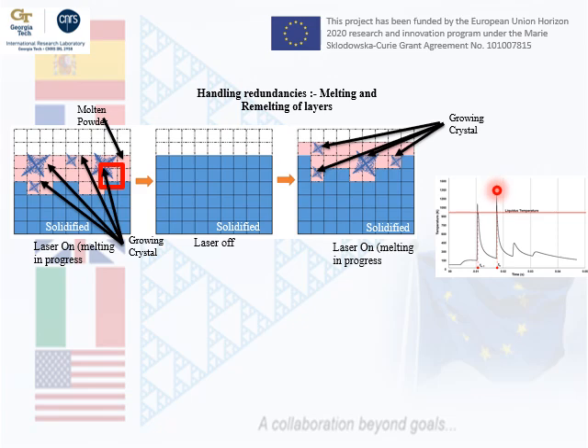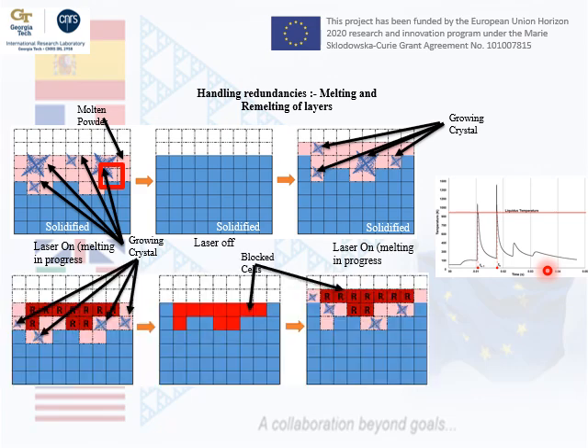Any growth that we observed before is going to disappear, so that memory has to be reallocated, and this is going to cost more time. Then solidification is going to happen again, and because we don't have any further remelting process, solidification is going to be permanent, in the sense that during the additive manufacturing process we're not going to observe the melting of the cell again. Again, this costs time, so this is what we would like to avoid. So what we did is utilize a different algorithm, as I mentioned before, and because we already have pre-calculated the temperature of each cell, what we are going to do is simply go back in time.